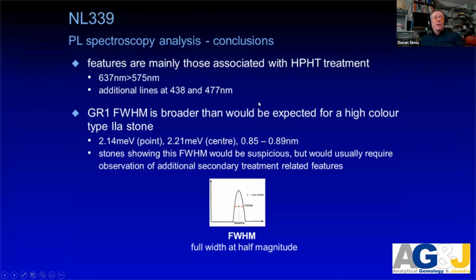And the conclusion: the features are mainly those associated with HPHT treatments. This is, at the time, 637 larger than 575, and additional lines at 438 and 477 nanometers. Full width at half maximum, what it means is just the width of the GR1 center, and it can be measured, and this width is larger than it should be in natural stones. And that's it about these stones.